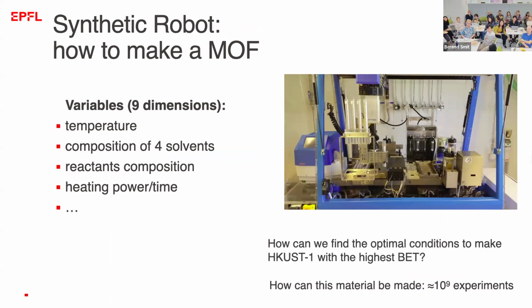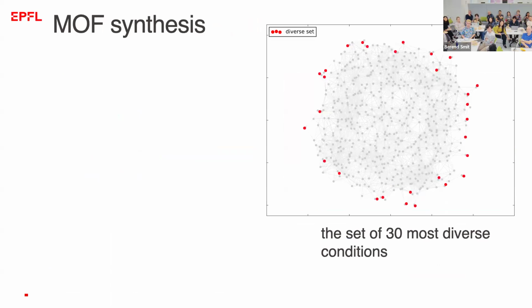So how do you sample that? What we wanted to do is really a sort of an unbiased sampling. So the very first thing we did is, how do you initiate this robot with 30, again, most diverse samples. You have the experimental conditions, you scale the experimental conditions from 0 to 1. And then you measure the distance between 2 points. If the distance is close, the experiments are similar. If it's far apart, they are very different experimental conditions.